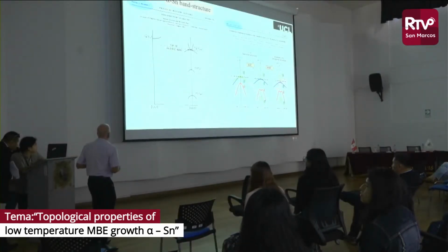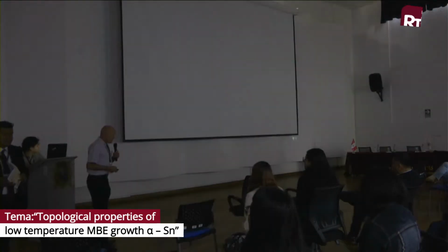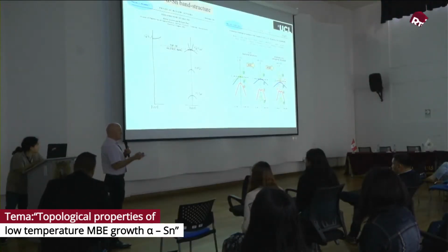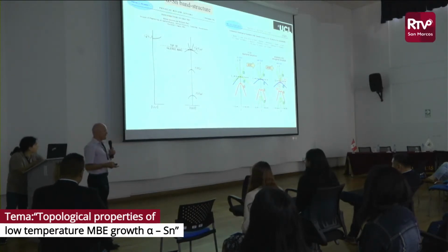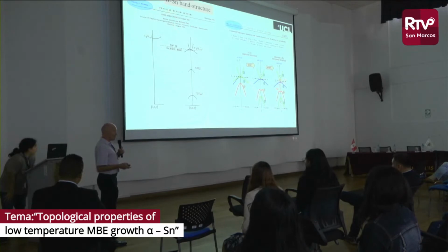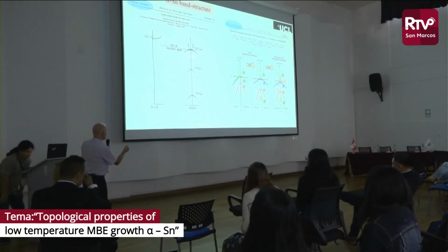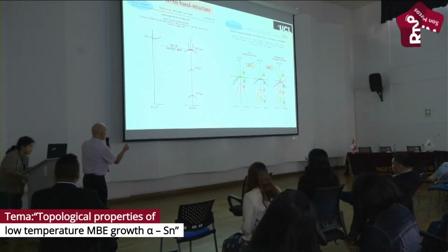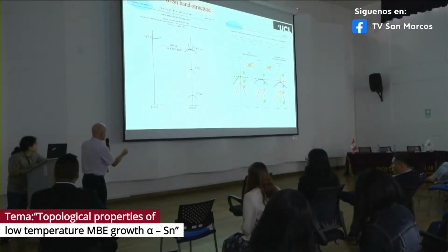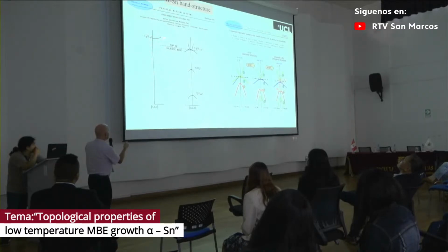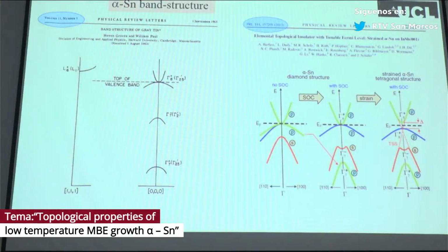What they also did was a calculation. They compared it with the crystalline structure of germanium, and kind of extrapolated what tin would look like, based on their simple transport measurements under hydrostatic pressure. So this is the top of the valence band here, we've got the conduction and valence band here, we've got other bands deeper into the valence band, we've also got a subsidiary minima at the L point, which is not quite conducting, but may be relevant when you are applying strain or pressure.